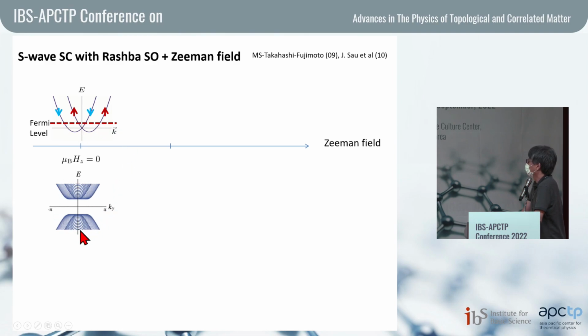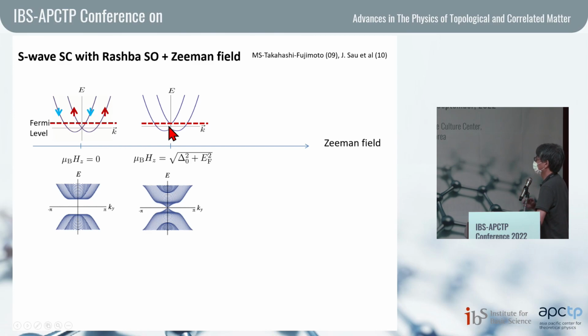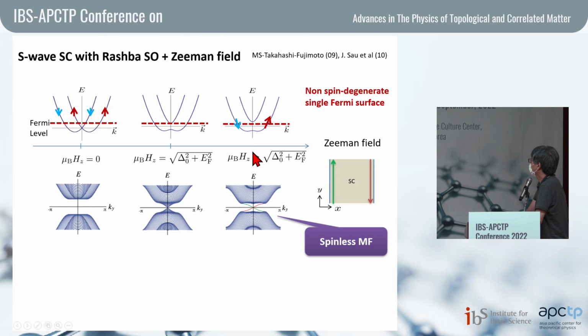And correspondingly, here I show the quasiparticle spectrum in the superconducting state with a boundary. As you can see, we only have a superconducting gap, like an ordinary s-wave superconducting state, and there is no edge state. So this is a non-topological state. On the other hand, if you apply the Zeeman field, we have a different situation. Once we have a Zeeman field, we have a gap at the gamma point, so that we can push one of the Fermi surfaces above the Fermi level. At a particular value of the Zeeman field, the topological phase transition occurs. And then if you have a larger Zeeman field, we can realize this situation in the normal state. In this case, we only have a single non-spin degenerate Fermi surface. So correspondingly, on the superconducting side, we have spinless Majorana fermions. This behavior is also very consistent with our simple Fermi surface criterion.